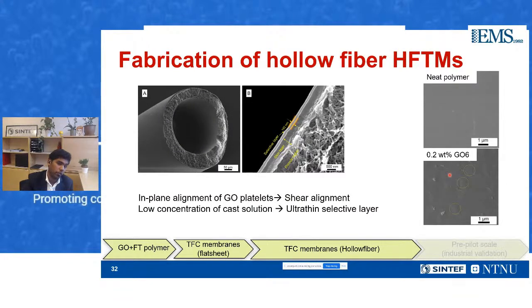So we fabricated them into hollow fibers. Here we used a different coating mechanism, which is dip coating. And we were able to achieve the same in-plane alignment of graphene oxide in this system as well. The reason is not the surface energy that we spoke about in the mechanically forced alignment in the flat sheet. Here it is because of shear alignment. When we dip coat the nanocellulose, the graphene oxide platelets orient themselves towards the surface so that they can have shear alignment, and it still retains this in-plane alignment of graphene oxide. With a low concentration of the coating solution, we were able to coat a thin layer up to 190 or 200 nanometers in thickness on top of the porous support.